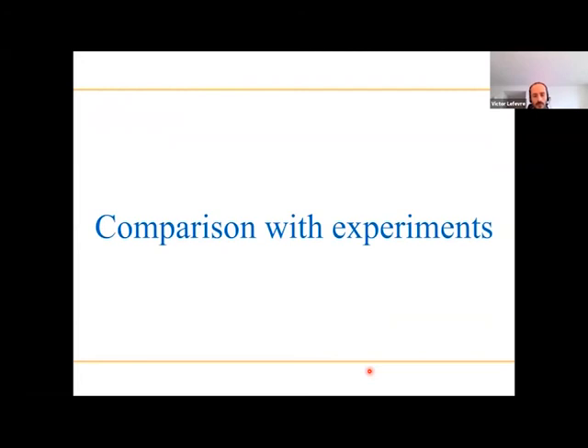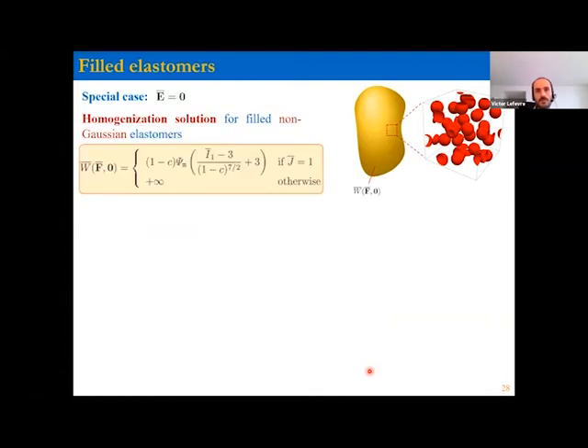All right, so we have the model, we have the solutions, we have a good idea of the behaviors of these materials. Now let's compare with some experiments and see how well these models work. First we're going to look at the pure mechanics case. We're going to leave the electric field switched off and look at the case of filled elastomers. In this case, the solution reduces to this expression. Again, it's fully explicit. Once you know the behavior of the matrix, psi m, and the volume fraction of rigid particles, that's the behavior.